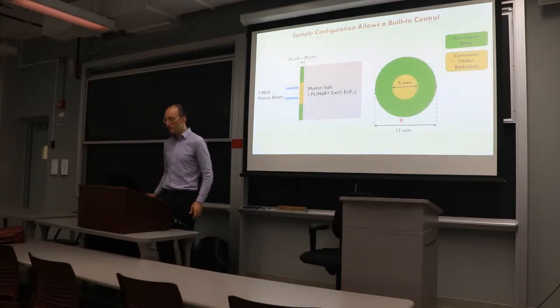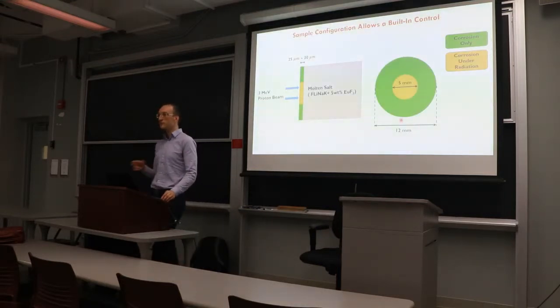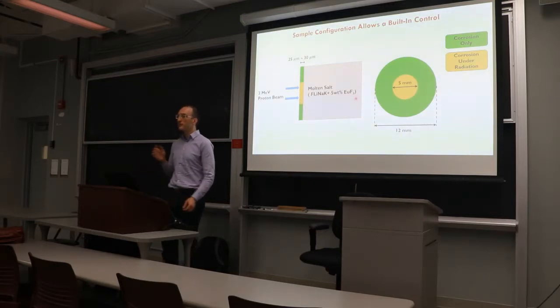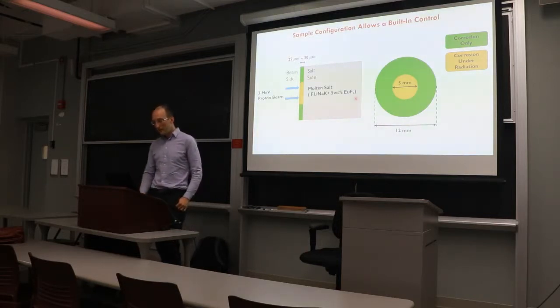And just to show you another cross-section of what I'll explain later, there'll be a region in green that only sees salt corrosion. There'll be a region in yellow that only sees corrosion and irradiation. The salt we use is FLiNaK plus europium fluoride, and that's to pull the corrosion potential down to simulate salt fuel, which is a lot more corrosive than clean FLiNaK or clean FLiBe. So we went for a worst case scenario, like if somebody wants to build a molten salt fueled reactor, what's it going to be like? And so here's what happened.